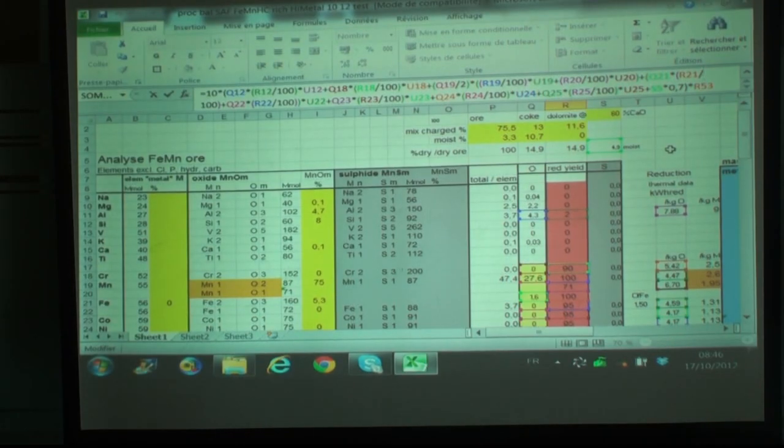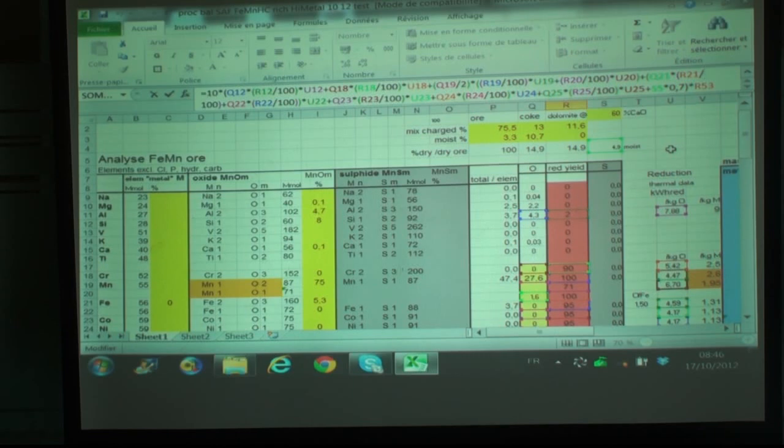Vaporizing water requires 0.7 kilowatt-hour per kilo. Here again, if you want, you can insert a better formula, but normally the moisture heat is small against everything. But it's better to use it than to do nothing.